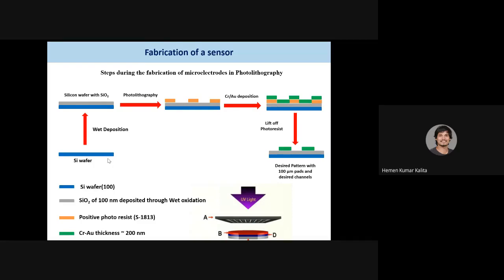There are obviously some other differences, like wet deposition is easier as compared to dry deposition. So here we have used the wet deposition to deposit around 100 nanometer of silicon dioxide layer on the top of the silicon substrate. After that, this step is the exposing step in the photolithography. How we have done it, you can see at the bottom there is a small image where there is a UV light, and A is the mask through which the light will pass, and B, C, D is the substrate. C is the silicon substrate, D is the silicon dioxide, and B, the red color, is the photoresist. Photoresist is used on the top of the silicon dioxide.